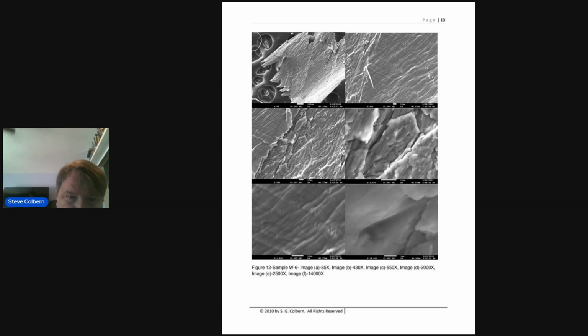Here's sample W6, and you can see the layered structure again in this. And it would be very interesting to do electrical measurements under SEM. I think that's possible nowadays, but that's really high end. We weren't able to do that during this analysis, but I think that with some of these samples, doing electrical measurements under SEM with various parts of the material, seeing if there's anisotropic resistance, different resistance one way versus another in the sample, and perhaps doing fast atom etching, followed by EDX mapping to see how the structure varies with depth in the material. Would be very interesting to see if there's a 3D structure to it. I strongly suspect that there is.